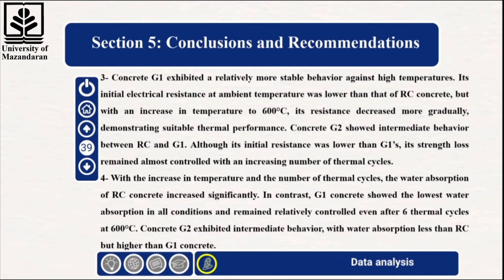4. With rising temperature and the number of thermal cycles, water absorption in RC concrete increased significantly. In contrast, G1 consistently exhibited the lowest water absorption under all conditions, remaining relatively stable even after 6 thermal cycles at 600 degrees Celsius. G2 again showed intermediate behavior, with water absorption lower than RC but higher than G1.